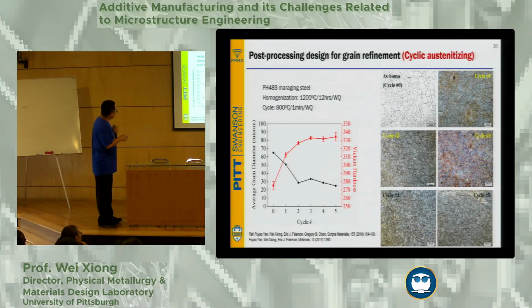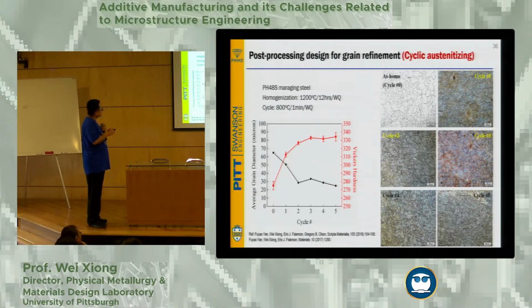So what's the consequence? As you can see, this is the average prior austenite grain size. With one cycle you get reduction, two cycles reduction, three cycles - but you have a limitation with the new nucleation sites introduced by martensite cyclic transformation, so you reach a plateau.